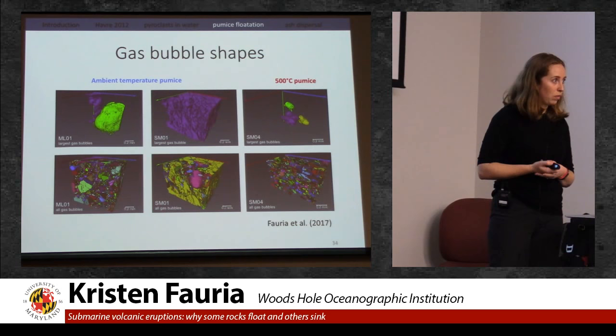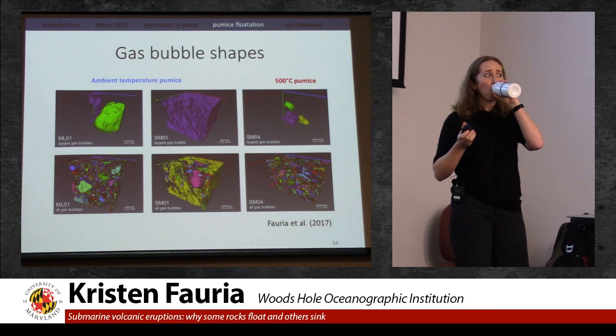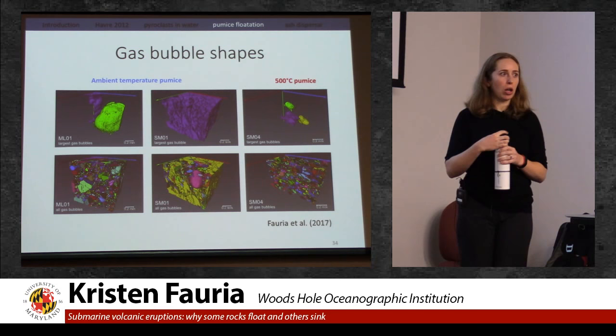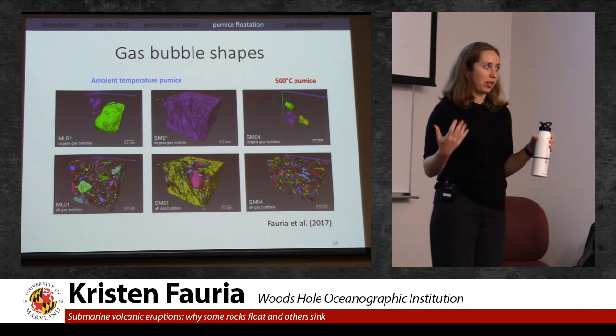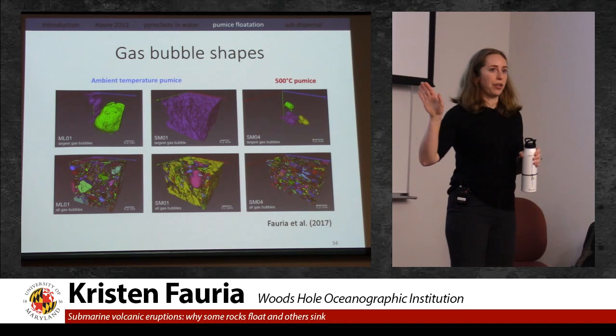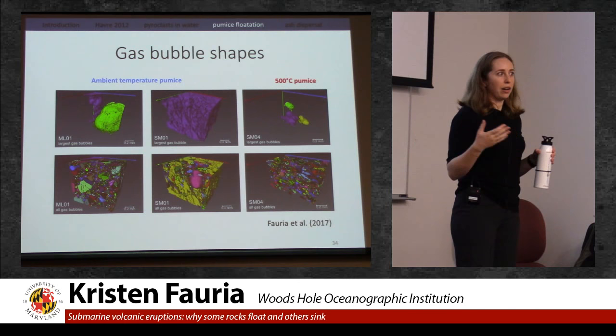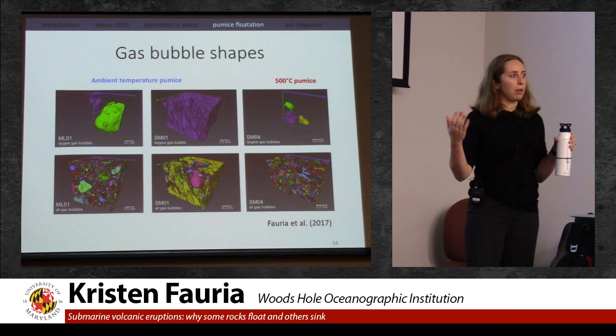Yeah? Is the gas in the natural materials in the rafts, is that volcanic gas or is that atmospheric gas? So if it's a submarine eruption, initially the gas will all be volcanic gas. And volcanic gas is mostly water, so it's steam when the pumice is hot, or it can be CO2. And this gas trapping process only occurs with a non-condensable gas like CO2 or air. And so inherent in the observation that the raft can float is that once a steamy pumice reaches the surface, it has to be able to ingest air in order to be able to float. Or it has to mostly contain CO2.